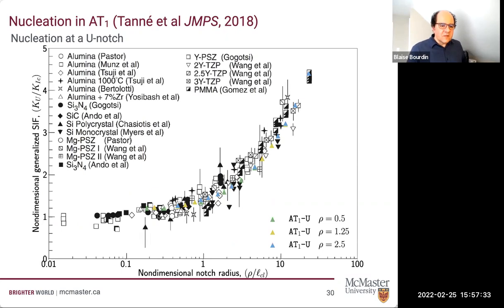We can do the same thing. So I'll finish with this. This is the same story, but with a U notch, which is even more challenging because there's no stress singularity or anything. But there's this nice picture that shows essentially some scaling law for 18 types of materials, the nucleation over a U notch.